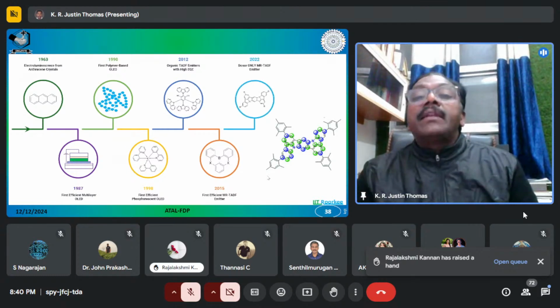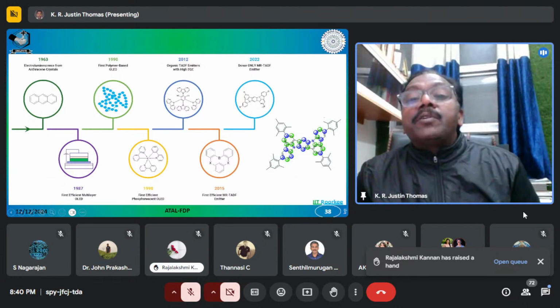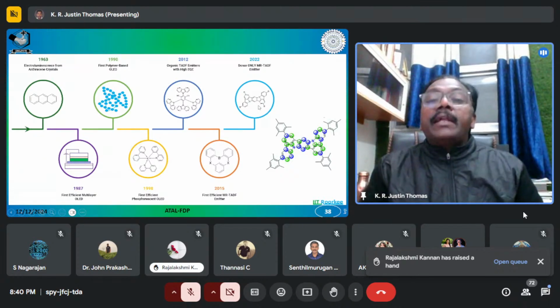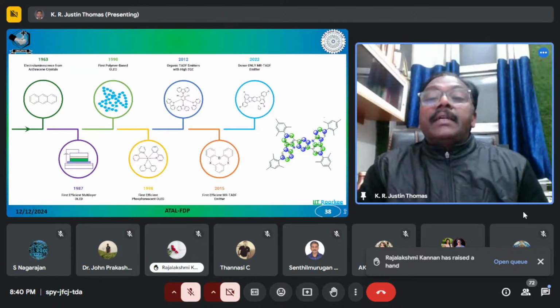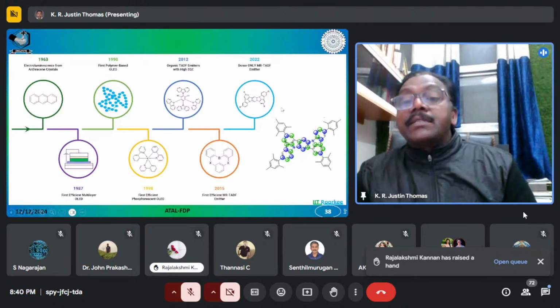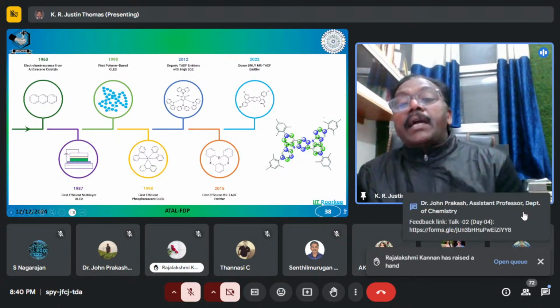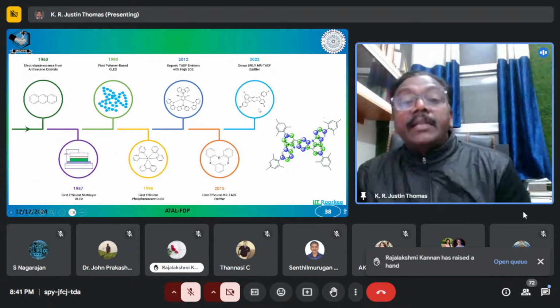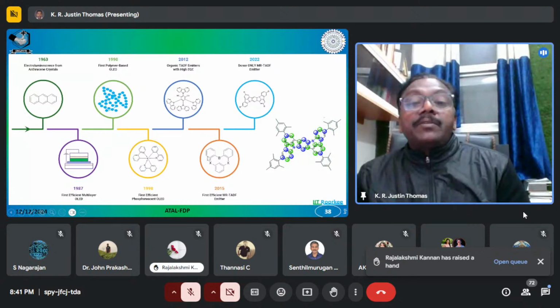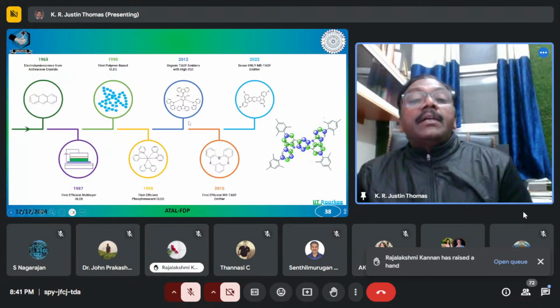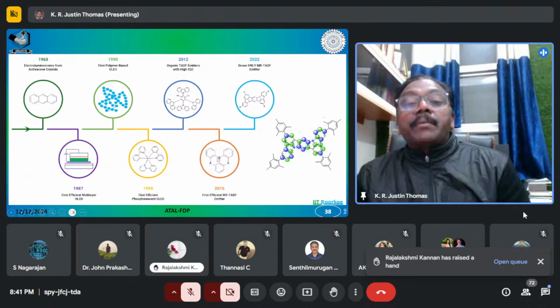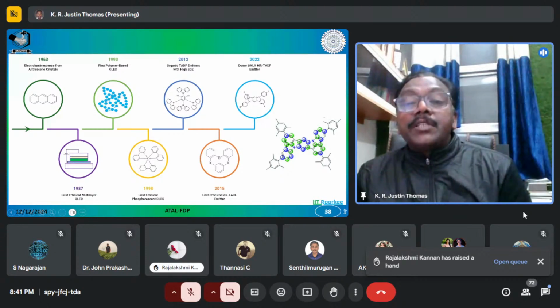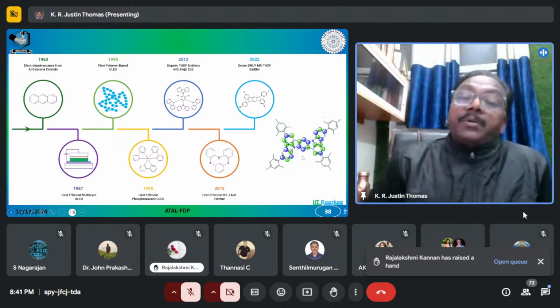That is what is reported recently in 2022, that this molecule, which is having a fused structure with one heteroatom such as nitrogen, is capable of showing MR characteristics, that is, donor groups, donor in certain atoms and acceptor at certain atoms. Okay, so as I have illustrated here in this molecule. So this is an important outcome in the sense that certain limitations of these molecules can be avoided in this one. That is, charge transfer reduces the fluorescence quantum yield to some extent. That can be reduced in this one because there is no charge transfer characteristic in this molecule.